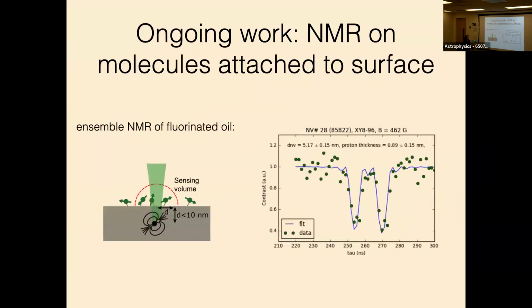Okay, so our ongoing work is to now try to sense something that we intentionally put on the surface with NMR. For example, this is just a proof of principle thing where we can intentionally put perfluorinated oil on the surface and we see this clean fluorine peak next to our hydrogen peak. So now what we're trying to do is put some big fluorine group and then do the same exact experiment.